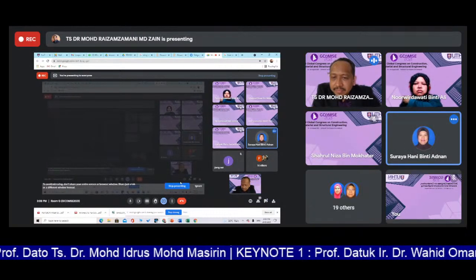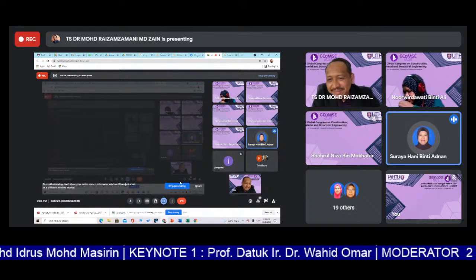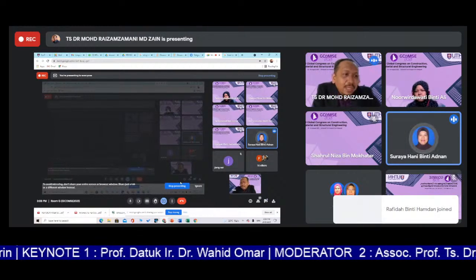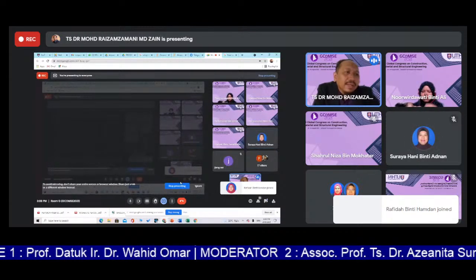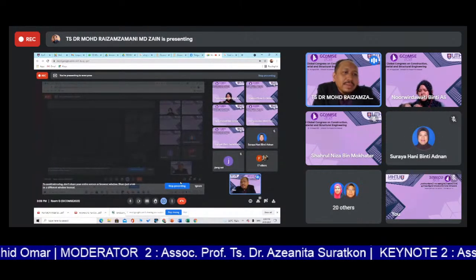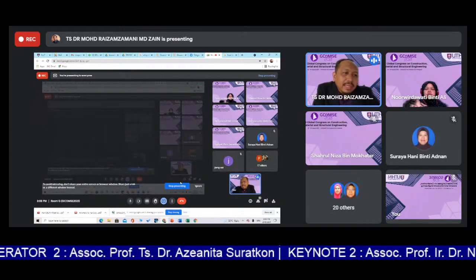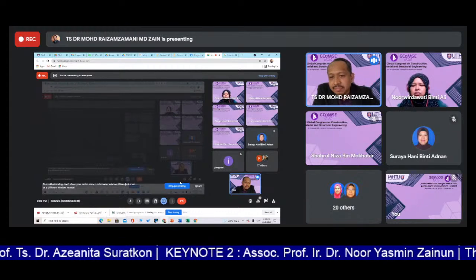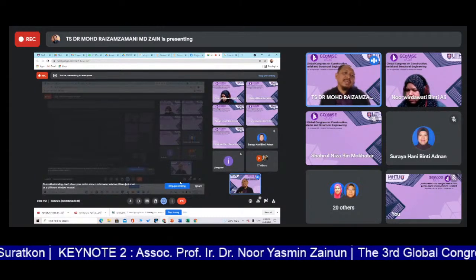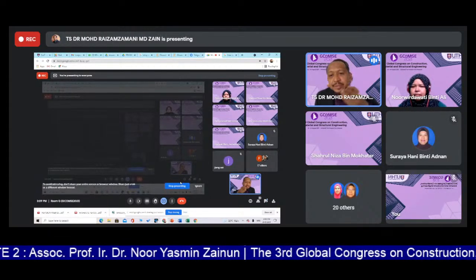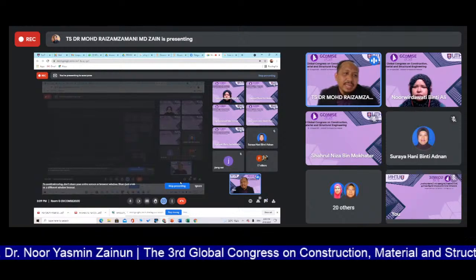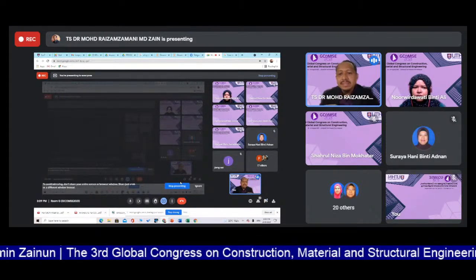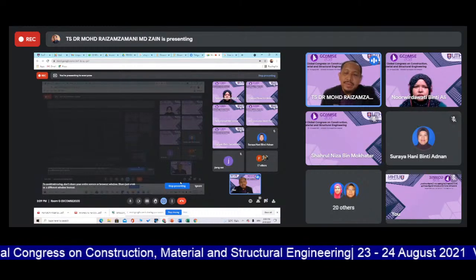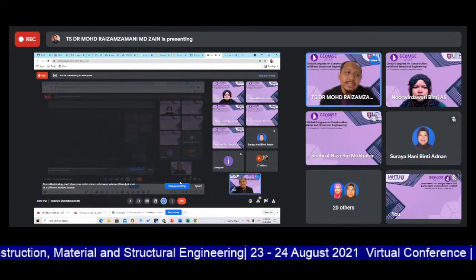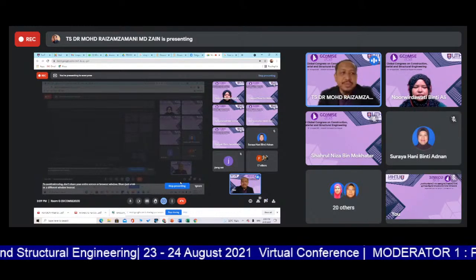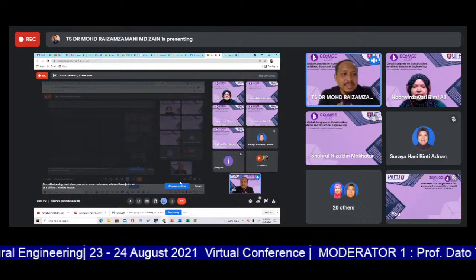For the next question, why do you use the recycled concrete aggregate as the fine particles? As we know, the disadvantage of RCA is that it contributes impurity. Based on my research, I can say that when you add RCA into the ECC sample, it contributes to a reduction in concrete strength, because one of the reasons is the prevalence of impurity in the RCA.